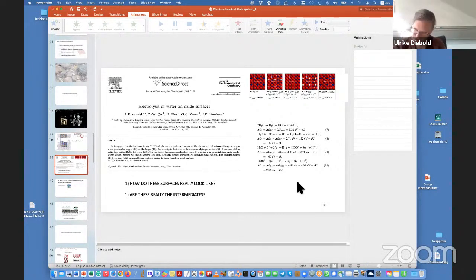And then you're lost, because once you have that, with the very sharp tip, it's not only the last atom that interacts, but other atoms at the tip. But in principle, yes, you can certainly look at amorphous structures. Have we done it? No. Other people have. For example, this nice work from Freund on amorphous silicate overlayers, where they have really seen how these glass structures form. And when you say flat for STM, you mean atomically flat over hundreds of nanometers? Yeah, ideally. The flatter, the easier. Okay.